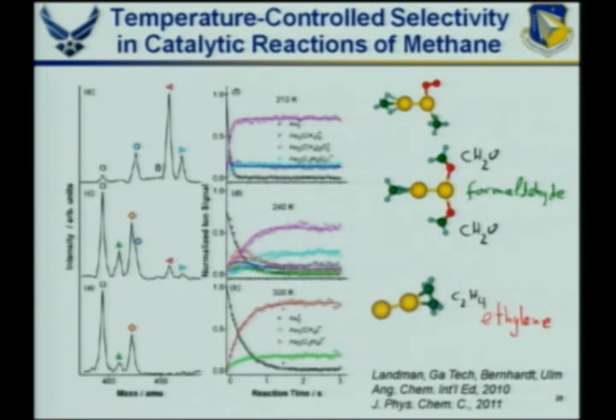Another way that you can control this catalytic chemistry, interestingly, is with temperature. This is work using gold dimers as catalysts for methane. And it turns out that you can have the oxidation or very low temperature combustion of methane. At higher temperatures, at room temperature, if you put in methane and oxygen in the system, you just find that the methane reacts to form ethylene. But at low temperatures, oxygen sticks to this system, and the methane gets oxidized to formaldehyde.